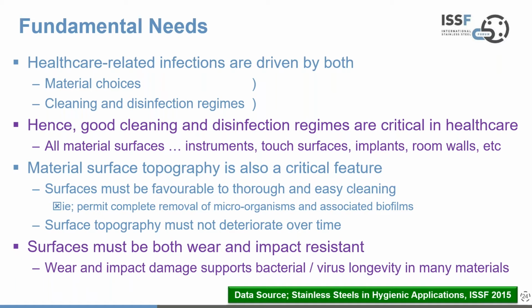And what's important here, and I touched on this earlier, is the surface topography of the material. It's a critical feature because the surfaces need to be favourable to thorough and easy cleaning. And what we mean by that is complete removal of microorganisms and associated biofilms that support the growth of those microorganisms. And equally, over time, that surface topography must not deteriorate. Furthermore, the surfaces must be both wear and impact resistant, because wear damage and impact damage actually supports bacterial and virus longevity in many materials. So that's an additional feature on top of the surface topography.